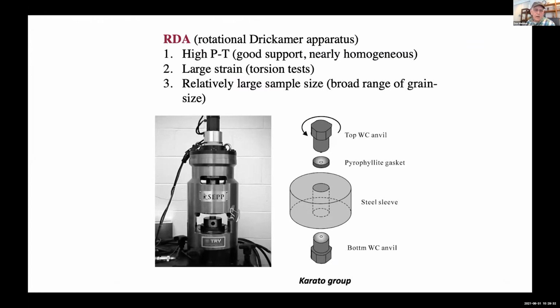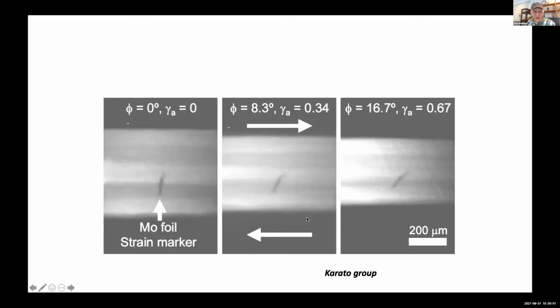Also being used at our beamline is a system by the Karato group, a rotational Drickamer apparatus. This system is a uniaxial, or a vertical press axis in a Drickamer-style configuration of the cell, and the top anvil rotates relative to the bottom anvil, and it creates a pure shear stress on a sample at high pressure with a molybdenum foil here, allowing you to calculate the strain as the experiment continues.